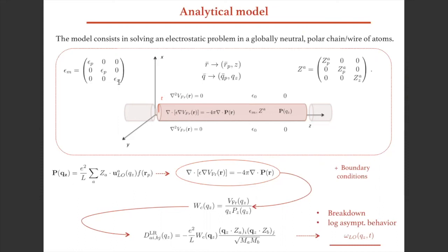I would like to interpret somewhat differently what I listened to. Suppose we are exactly at Q equals zero, not looking at what happens at small q. Then in two dimensions, I would say the Coulomb interaction doesn't play any role. So you don't have any contribution to the restoring force in the phonon from the macroscopic field. I've not understood if it is the same even in one dimension. That means in one dimension, Q equals zero. Of course, you have a longitudinal-transverse splitting, which is due, as you say, to the different mechanical properties of the oscillation. That's clear. But suppose that on top of that, I want to add the Coulomb interaction. Of course, this may only concern the longitudinal ones. But if Q equals zero, there is no effect. Am I right? Exactly. It's making 2D just different asymptotic behavior. Yeah. Okay. Thank you.